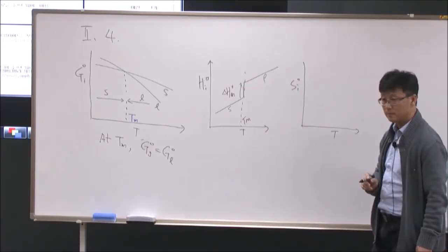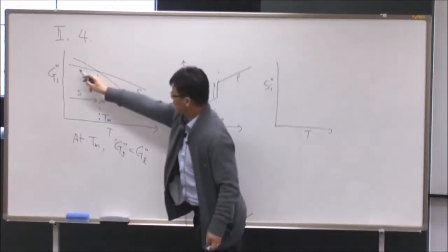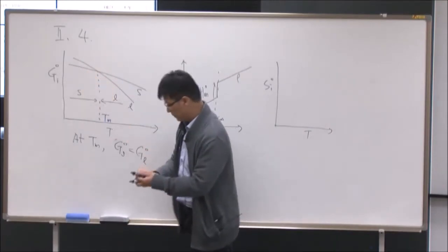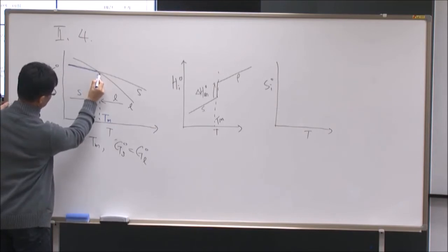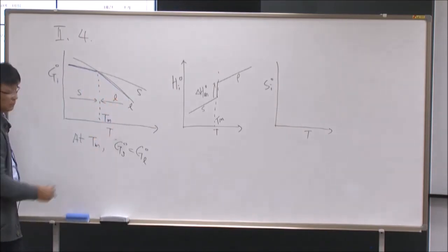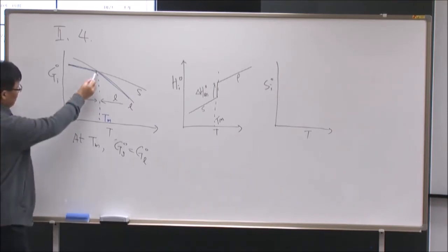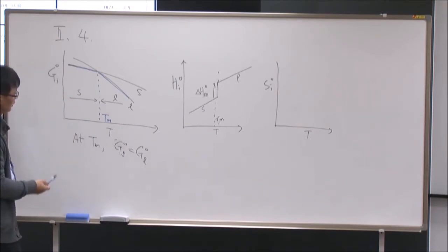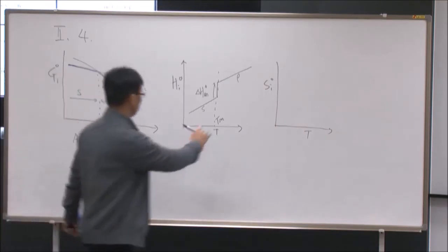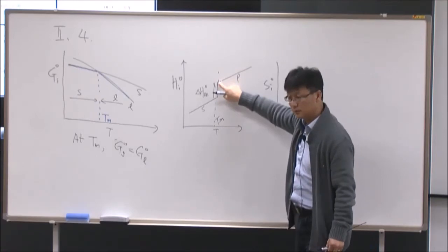In terms of the Gibbs energy function, it's a continuous function. So this is stable in terms of the liquid phase. This is stable, and then the Gibbs energy changes this way. But it's continuous. The slope changes abruptly at a certain point, but the Gibbs energy itself is continuous. In the case of enthalpy, we have this discontinuity here. So this value, and then suddenly this value.